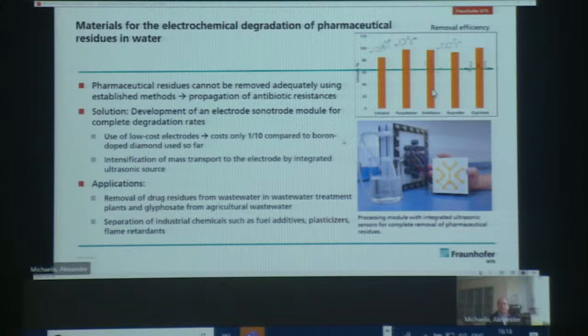What we also do is we do some fine cleaning, fine filtration of polluted water. Here it comes down to parts per billion pollutions, also only trace elements. For this, we don't use ceramic membranes. In this case, we use an electrochemical process along with ultrasonic treatment using piezo ceramics. And by this process, we are able to get rid of pollutants coming from drug industry. So we can clean remains of antibiotics, also remains coming from agriculture. For example, glyphosate is here a big subject.